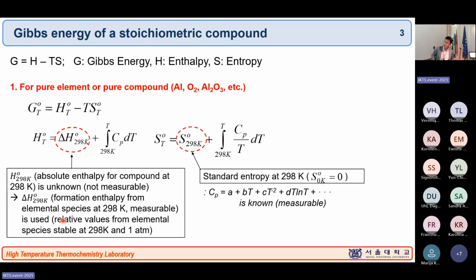So now this is the Gibbs energy for the pure species. When I say pure, it's stoichiometric. It's not like solution species like FCC, BCC, or liquid slag. For example, CaO or MgO or Al2O3 or pure oxygen, Gibbs energy is all expressed in this way: G equals H minus TS. Everyone knows these terms, I don't want to explain. And here, especially, we have G naught, H naught, and S naught. This is the classical symbol we use to represent that this is the pure standard material species. So you have to know this.